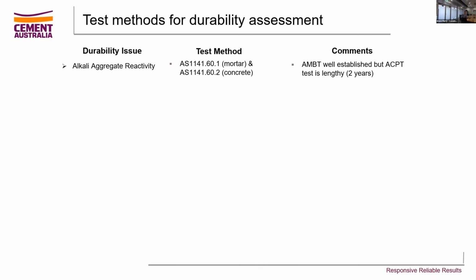So the first one, alkali aggregate reactivity. We're all very, very familiar with this phenomenon, not least of which up here in Queensland, where the infrastructure organisation has suffered hugely from a lot of support structures suffering from expansive reactions. The two test methods that are available today, AS 1141, 60.1 and 60.2, are designed to allow aggregates to be tested for potential reactivity under alkaline conditions, which is in concrete.